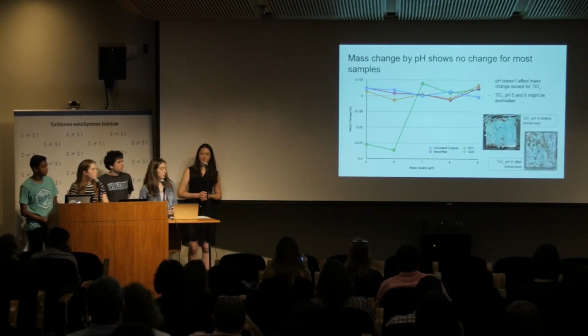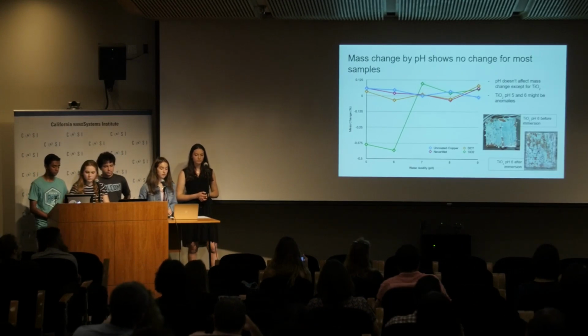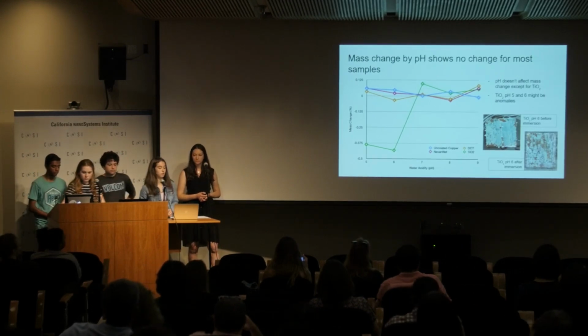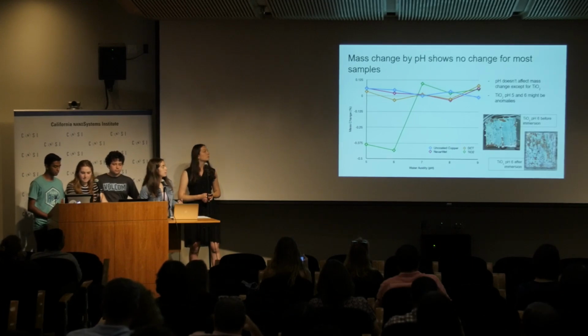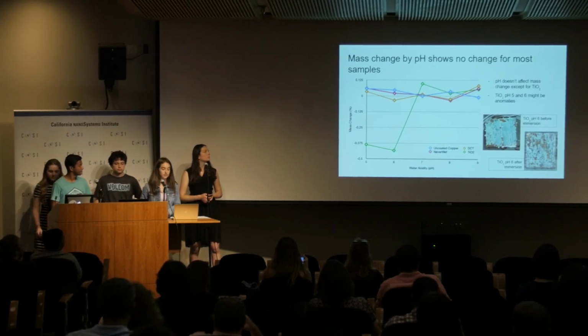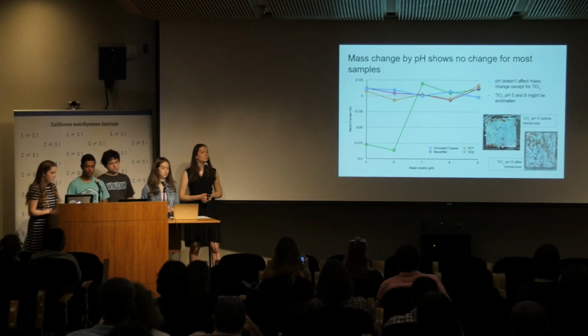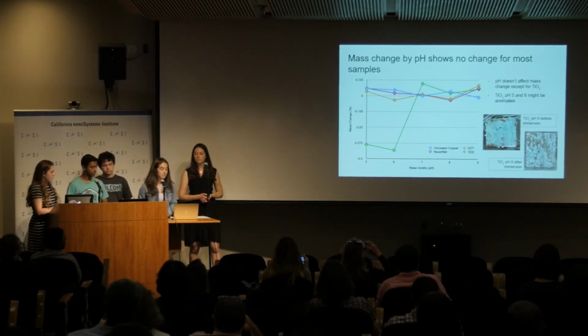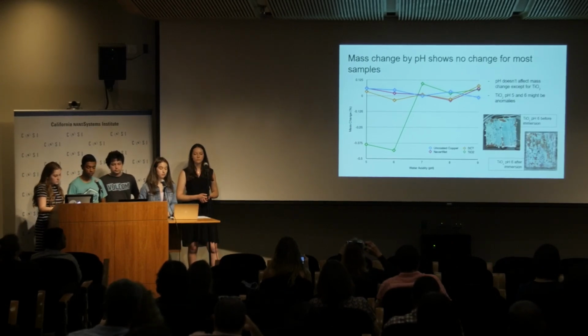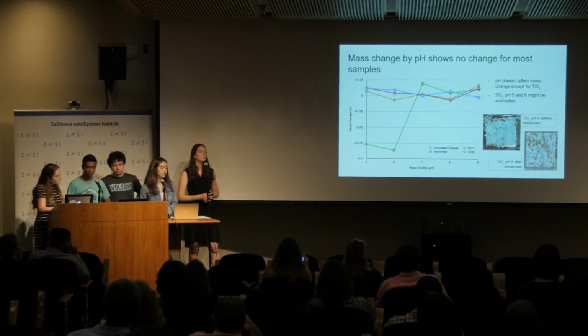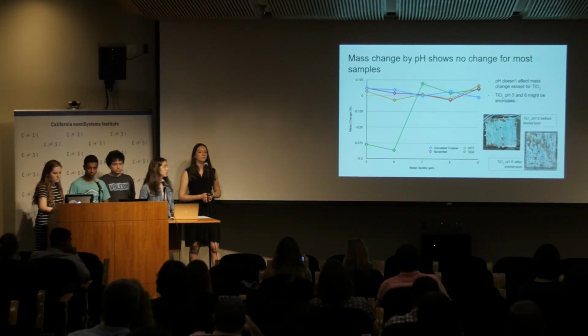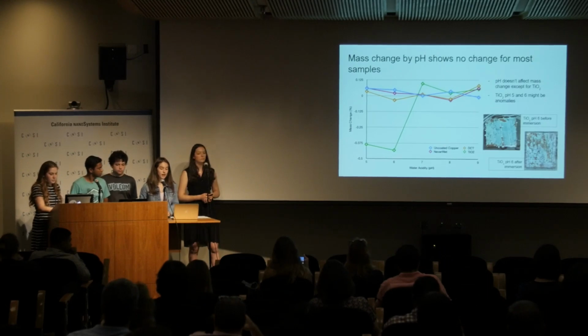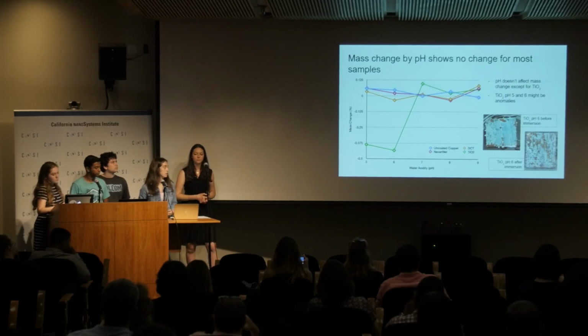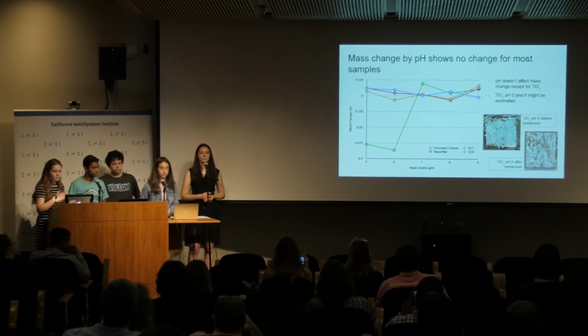So similarly, when plotting the mass change of the copper samples against the specific pHs they were submerged in, it was apparent that the pH did not significantly affect mass change except in the TiO2 sample, like I discussed in the last slide. However, the mass change results for the TiO2 samples were most likely anomalies that resulted from the degradation of the TiO2 film after leaving it in the acidic pH solutions overnight. However, more trials would need to be performed to confirm that these were in fact anomalies.